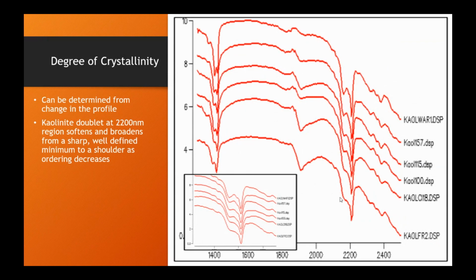This plot shows decreasing crystallinity in kaolinites. So if we go from top to bottom here in this 2200 area, you can see that the crystallinity is decreasing. But also note how the water content, which is at 1900 nanometers, right here, increases with decreasing crystallinity.